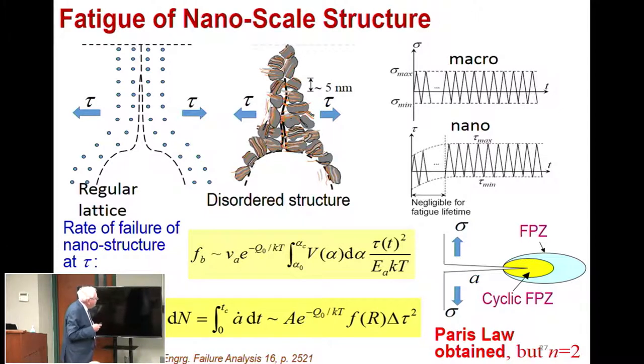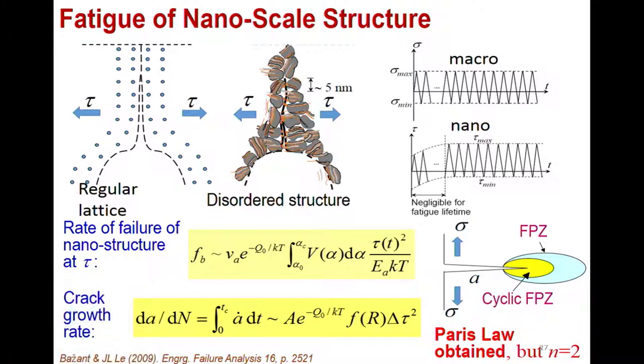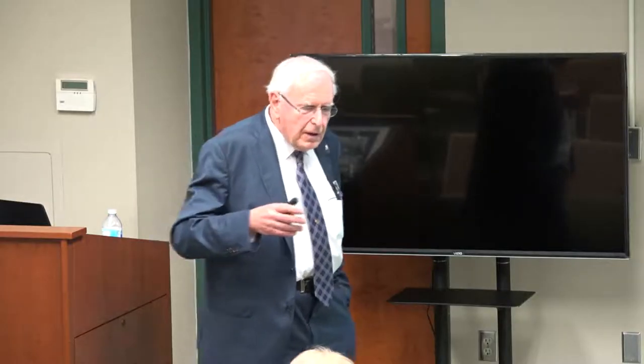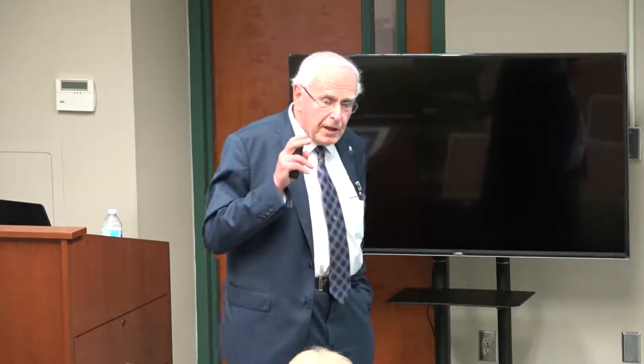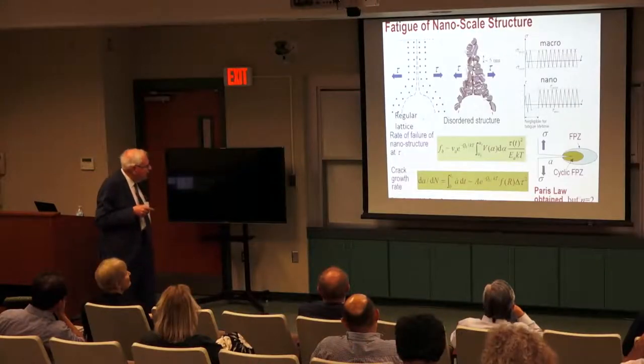The theory has been extended to cyclic and static fatigue. Now, then you have another case. You need to realize that if you take lifetime, right, and fatigue until failure, the crack grows, but grows subcritically. So it's not a question of the tail, but of the mean. And we have a well-known law, Paris law, for cyclic loading, or Charles-Evans law for static fatigue.